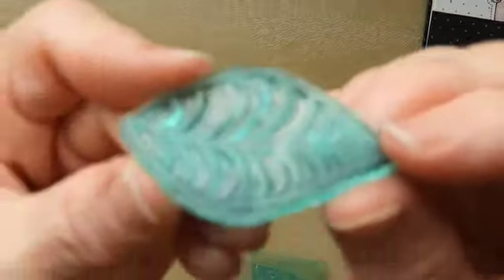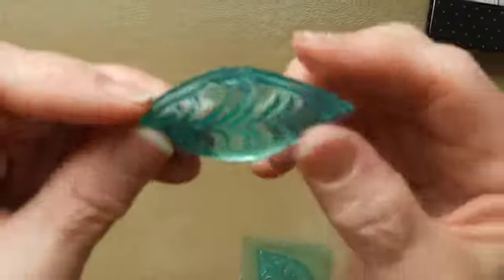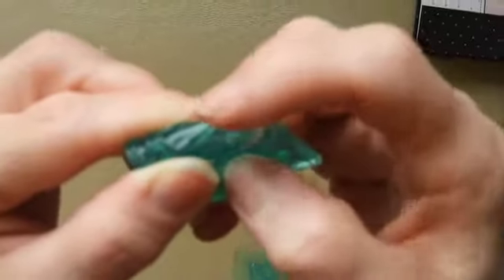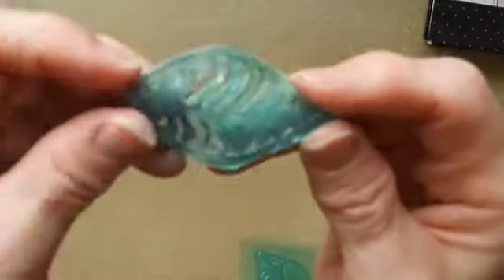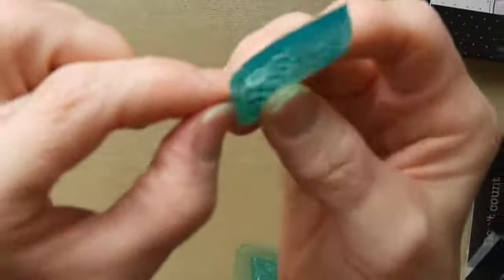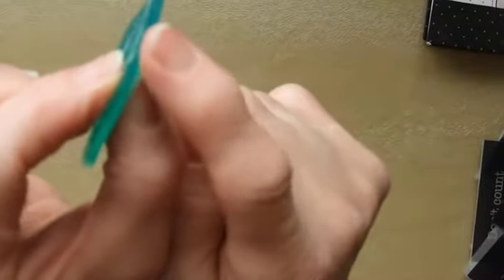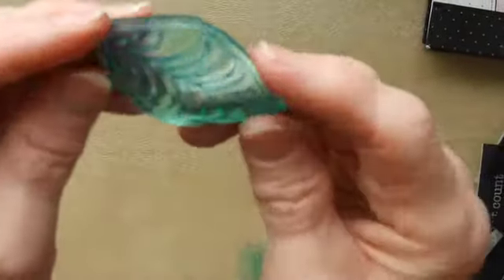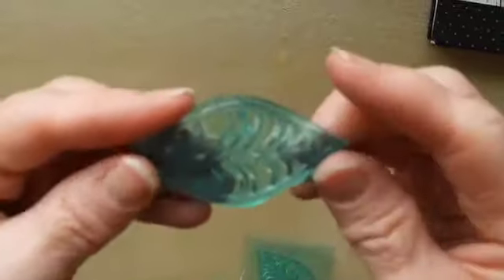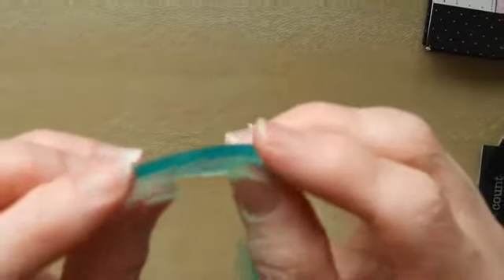Right, so I wanted to talk to you a little bit about over-curing and under-curing. Now this leaf would look to be almost right, but if I bend over, you can see that one of the veins is actually not attached to the back. So that is an example of under-curing. Now in this particular case, the back is definitely over-cured, and it's the front which is under-cured. So basically on this one, the back time was way too high and the front time wasn't high enough. Now if there were gel there to be washed away at the time, then the chances are the overall time is okay. So it's just the way that it's split that might need to be altered.